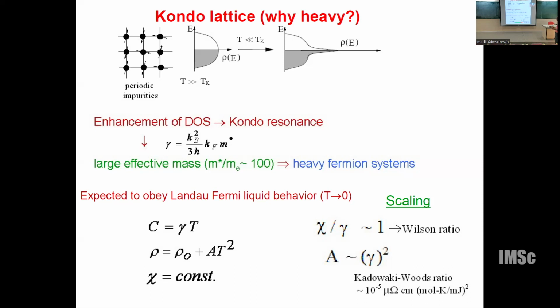This is how the density of states is enhanced. As a result, your linear term goes up. When you compare to copper metal, this is 3 orders of magnitude larger, therefore the linear term is larger. That is how the electrons become heavy; this is basically effective mass. The linear term tells you about the effective mass of the electrons at low temperature. When it goes up by 3 orders of magnitude, that means the effective mass has gone up. They become sort of almost immobile, very loosely speaking. Am I right to use that terminology? Conduction electrons are very mobile. This one is immobile. They hybridize with everything. They still remain immobile. Therefore, they remain a really narrow band. Okay, so therefore, they have become very heavy electrons.